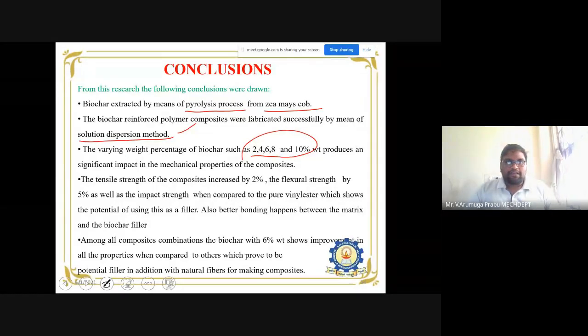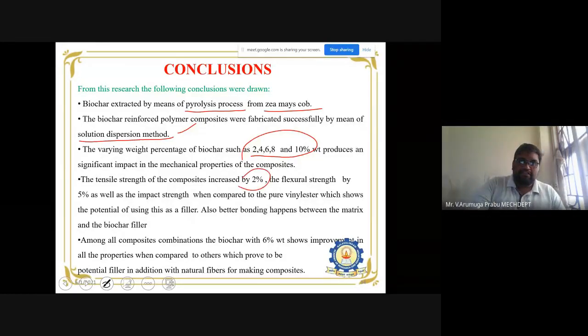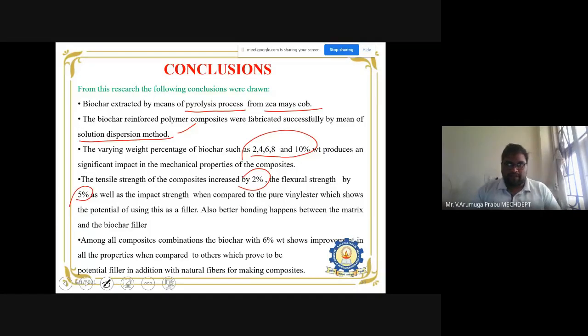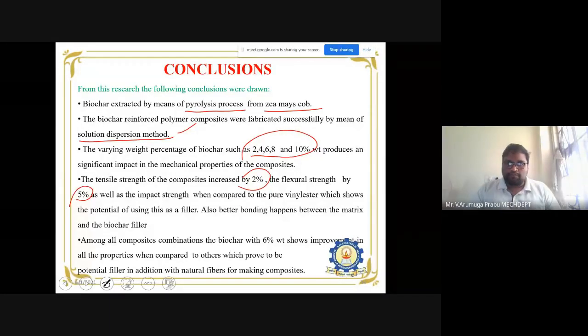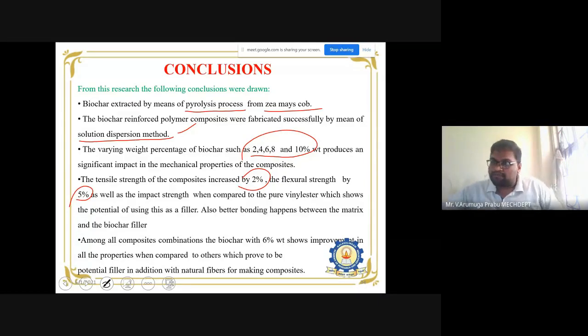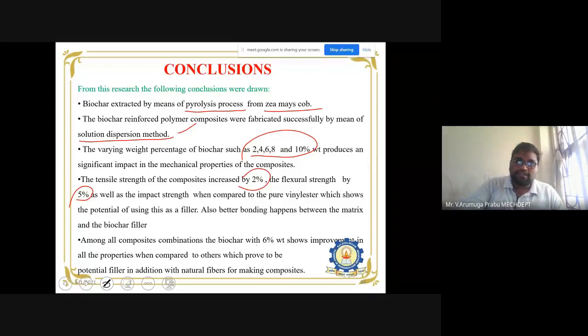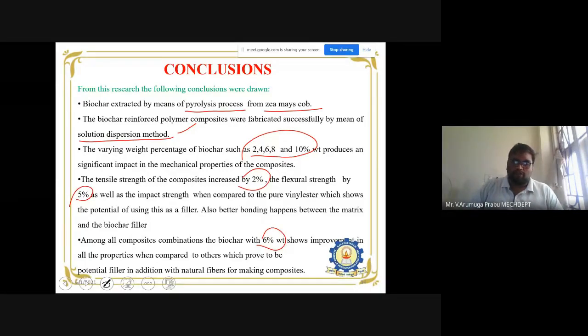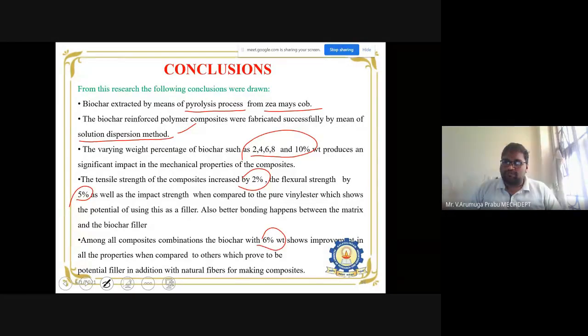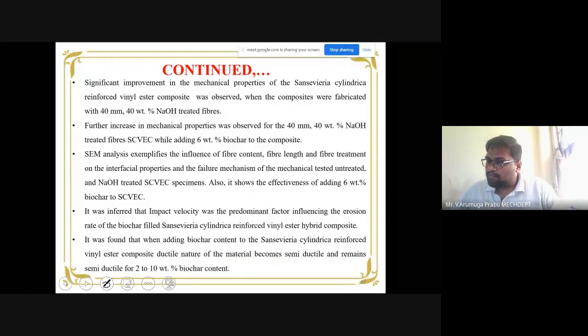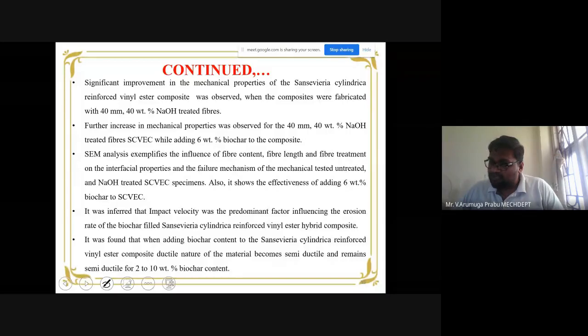Okay, and here the interesting thing we noticed, as I pointed out earlier, is an increase in the tensile strength by 2 percentage and flexural strength by 5 percentage when compared with the pure vinyl ester. Among all the composite combinations we prepared, exclusively the 6 percentage weight addition of biochar shows excellent results, which proved to be a potential filler in addition with other natural fibers for making some interesting advanced composites. Okay, that's the thing.